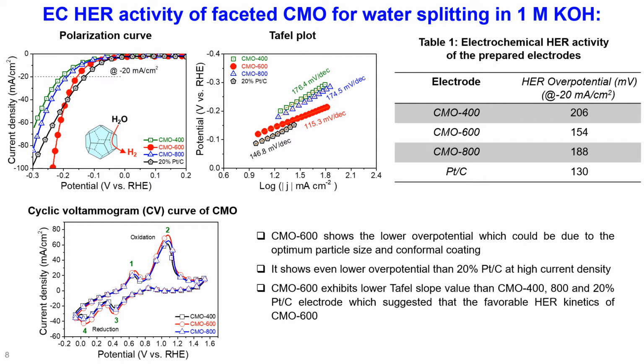Electrocatalytic HER activity of faceted CMO for water splitting in 1 molar KOH electrolyte solution. The polarization curve shows the HER activity of CMO 400, 600 and 800 along with the 20% Pt/C. Here we can see that the lower overpotential of 154 millivolt at 20 milliampere per centimeter square current density is achieved by the CMO 600 electrode, which is lower than CMO 400 and CMO 800 and much closer to the 20% Pt/C electrode. Also, the CMO 600 electrode outperforms the 20% Pt/C electrode at high current densities.